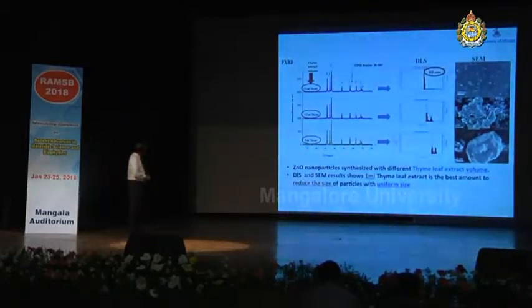And these are the powder X-ray diffraction patterns of the zinc oxides obtained, the SEM images, and the DLS, that is dynamic light scattering patterns to show the size distribution, and the thyme leaf extract and its concentration. Without any thyme leaves, you get such bulk, and as you increase, you get smaller particles, small size particles.